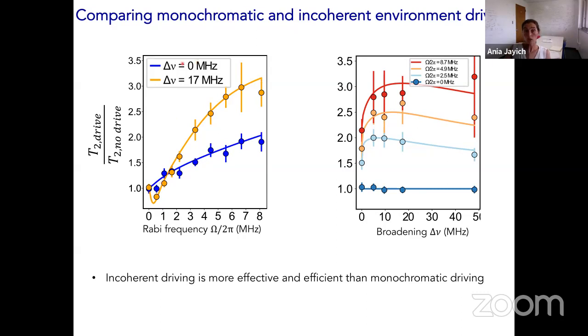We can also increase the coherence time with this coherent drive, as I mentioned, this monochromatic drive. We also see this increase in coherence, but what we've shown is this incoherent, this broadband drive is in fact much more effective and efficient at decoupling, at reducing the decoherence from the fluctuations in the surface spins. And this is just the T2 of the NV as a function of the broadening of our drive. So there's some sort of optimal broadening.